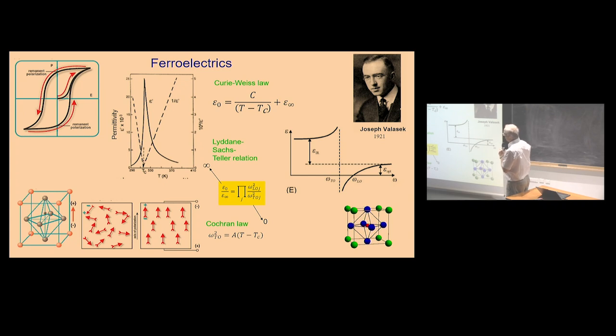So you can imagine that if we have such a Curie-Weiss law and permittivity goes at Tc to infinity, theoretically to infinity, then we should have the transverse phonon frequency going to 0. And this is the concept of the soft phonon described by Cochran in 1960, but actually it was published earlier by Anderson in 1959, and by Ginzburg even in 1948.